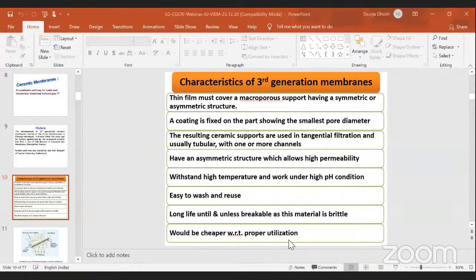The characteristic of these ceramic membranes is that there is a thin film which covers a macroporous support. The basic nature of the membrane is symmetric or asymmetric. However, mostly it is an asymmetric structure, wherein the coating is given to produce a smaller pore diameter. The membranes are available mainly in tubular configuration, but now also in capillary as well as hollow fiber configuration, and they allow tangential filtration. The membranes provide high permeability, and most significantly they can withstand high temperature and work under high pH conditions.